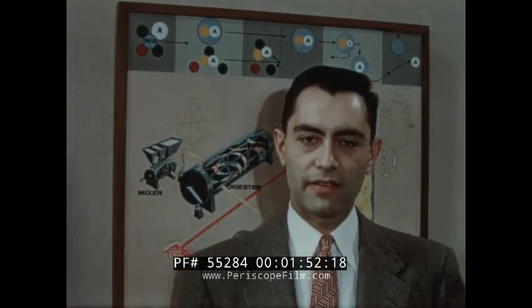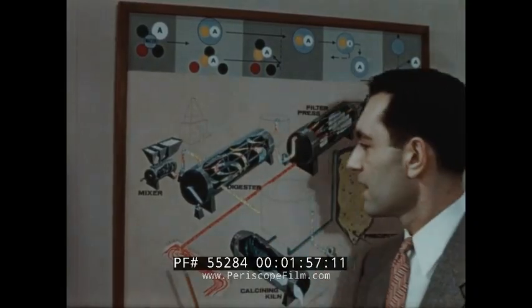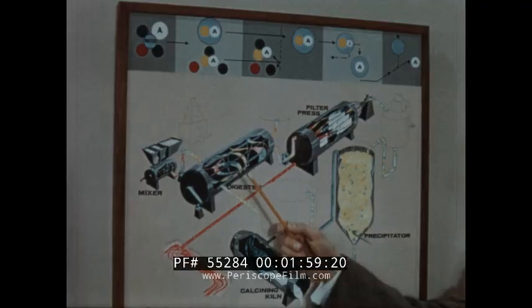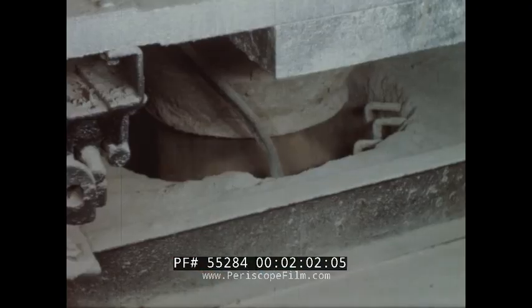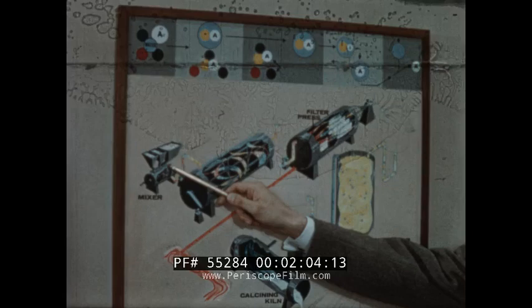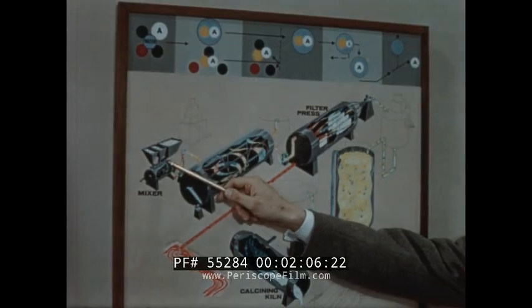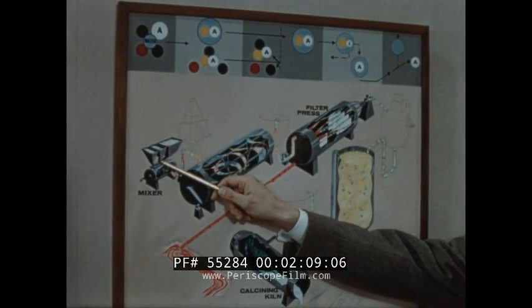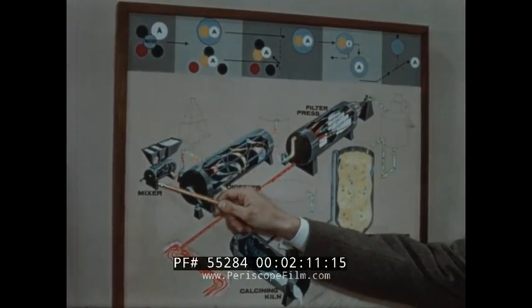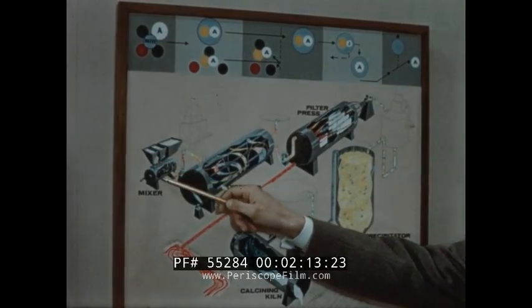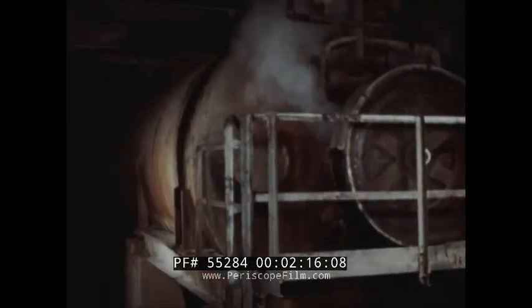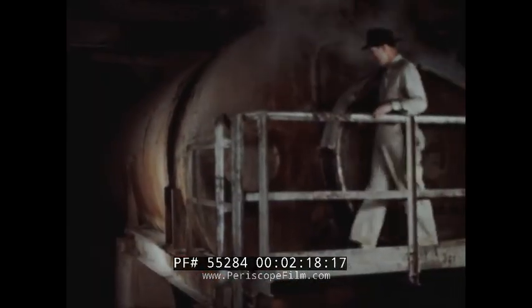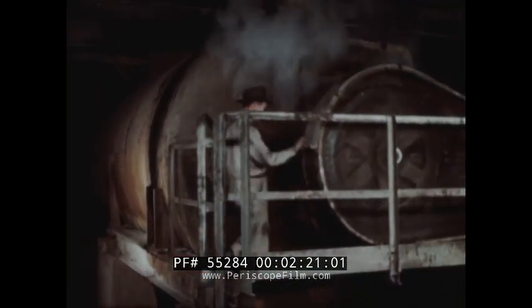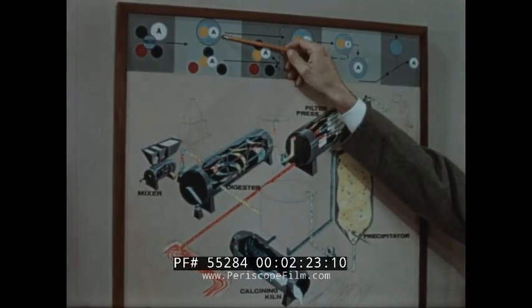aluminum. Now, we use what's known as the Bayer method, which is a chemical process containing several steps. After the bauxite has been ground to a fine powder, it's fed into a mixer with a solution of hot caustic soda, which we get by adding crushed lime, soda ash, and hot water. And then after this mixture has been thoroughly mixed, it goes into a digester. Here the alumina goes into solution as sodium aluminate, a liquid.